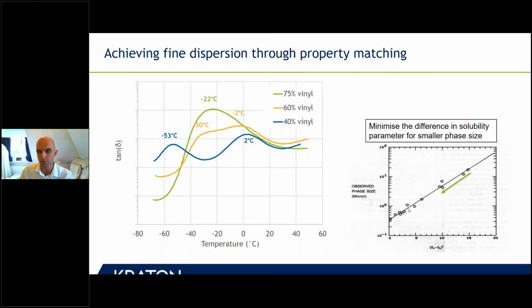So that also helps. Now, getting smaller particles can of course be done by putting a lot of energy in, through increasing the shear of your processing, but you would get far less stable systems. So once you apply shear again, you may lose that kind of behavior because you have a basically kinetically frozen equilibrium, and it's not really the thermodynamically advantageous state.